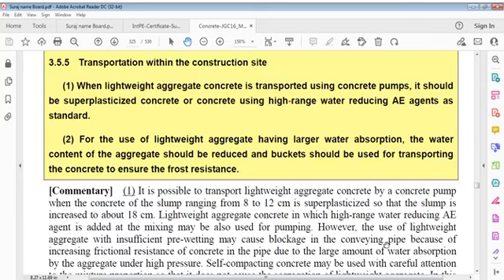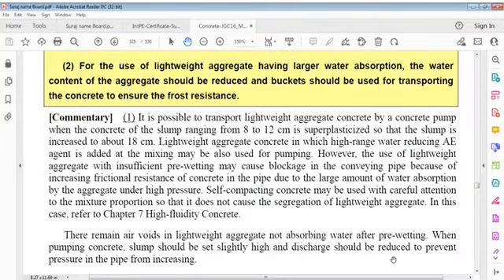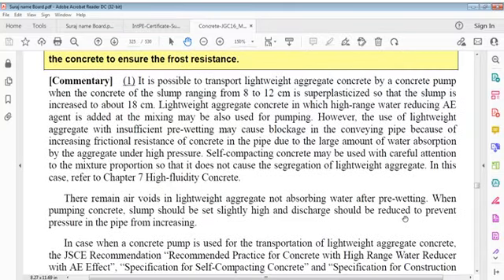When lightweight aggregate concrete is transported using concrete pumps, it should be superplasticized concrete or concrete using high-range water-reducing air-entraining agents as standard. For use of lightweight aggregate having large water absorption, water content of aggregate should be reduced and buckets should be used for transporting concrete to ensure frost resistance.